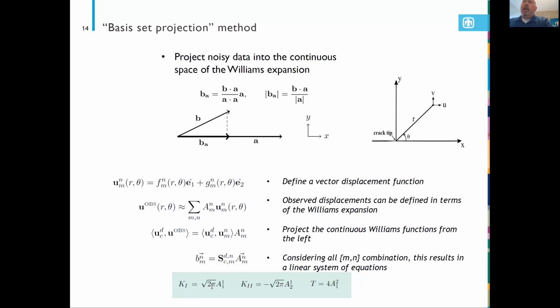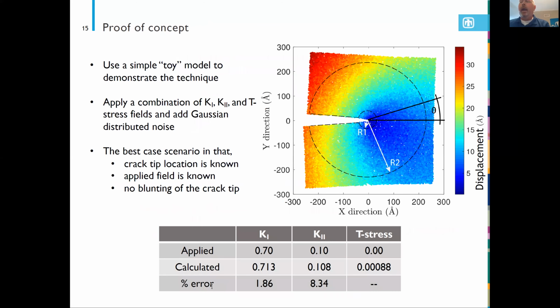Okay, so we have our model, and now the idea we want to try and get at is, well, what sort of error is associated with, for instance, this random noise that we will be seeing from atomistic models, and what sort of error is associated just simply with our methodology. And so what we did was we developed a toy model to explore behavior of the solution method. And once again, what we do is we take a series of points in a two-dimensional sense. We apply a known K field to it, or known stress intensity factors to it. And we use our methodology at that point to calculate what the stress intensity factors are determined as, right?